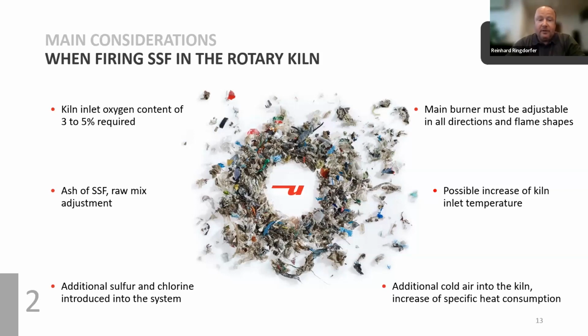Also, we heard before that depending on the secondary fuel you're using, you have to adjust your raw mix to get the desired results for your clinker quality, of course. Most of the time, if you're using RDF, some kind of plastics, anything else, you're introducing additional sulfur and especially chlorine into the system, which we all know tend to form cycles in the kiln preheater and can lead to blockages in the preheater itself. So this has to be considered.